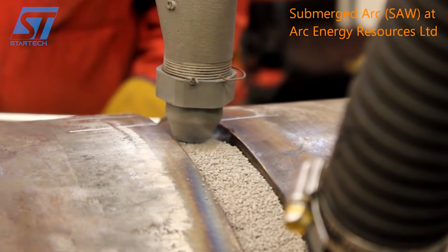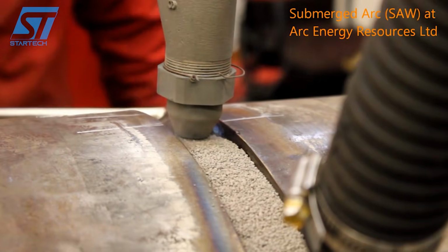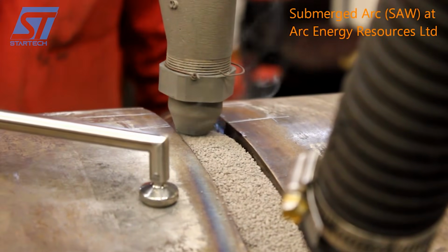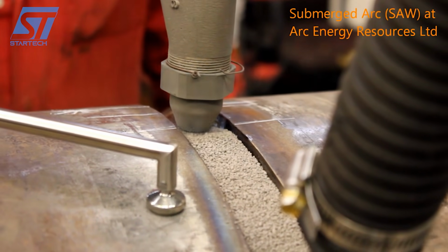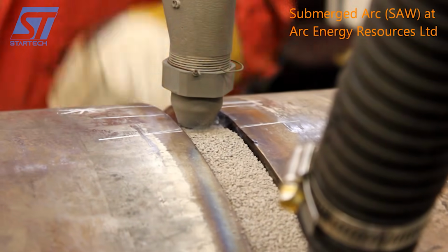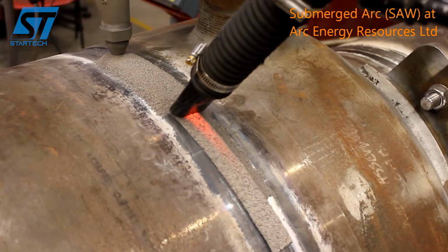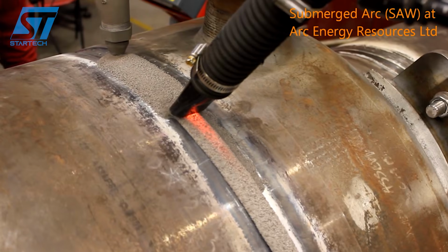That layer of flux does something remarkable. It acts as a thermal blanket, trapping the heat of the arc and allowing the weld pool to stay molten longer. This deeper heat penetration means fewer passes are needed to fill a thick joint, dramatically improving productivity.